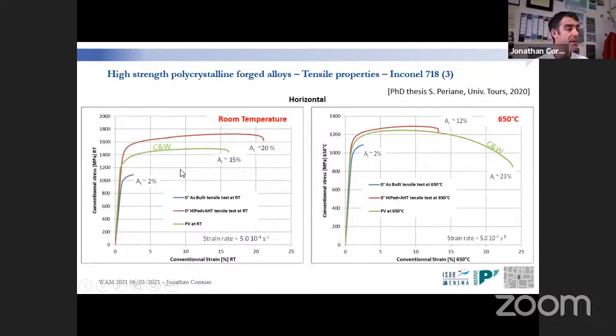temperature. Something I'd like to mention also, which is well understood now in the literature, is that even in the as-built state, we can see that we have quite high properties, and we come back to this later in this presentation, with a typical yield stress of nearly 900 MPa, despite the absence of any strengthening precipitates. And those quite high tensile properties in terms of yield stress are mainly coming from the very high dislocation density we have in the as-built state.